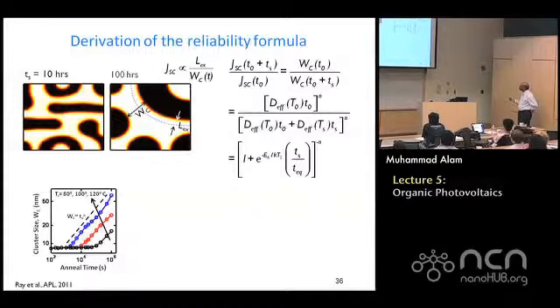So when you put them together, you get a simple equation that tells you that if you have a soft material that can go through each other very quickly, which is the activation energy, and you put it in the Arizona sun, then this whole thing is going to degrade very, very quickly, with the exponent n being 1/3. So to an extent you can actually predict how this is going to behave. One thing you can do is just say it is degrading, measure it, plot a few points and send it out in a report. But here you can essentially say exactly how this thing is going to behave as a function of time.